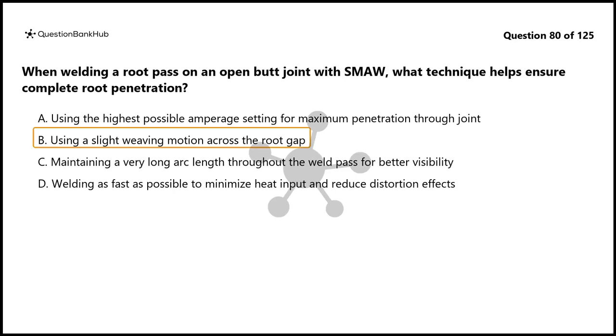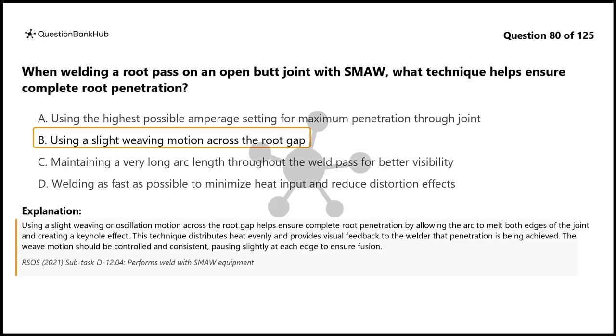The correct answer is B. Using a slight weaving motion across the root gap. Using a slight weaving or oscillation motion across the root gap helps ensure complete root penetration by allowing the arc to melt both edges of the joint and creating a keyhole effect. This technique distributes heat evenly and provides visual feedback to the welder that penetration is being achieved. The weave motion should be controlled and consistent, pausing slightly at each edge to ensure fusion.